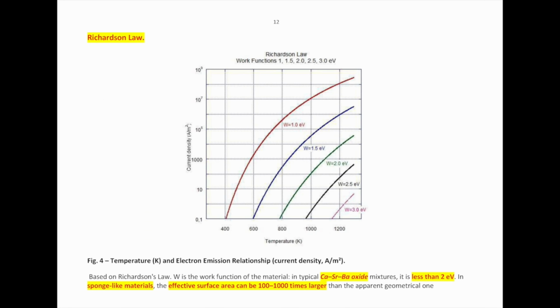Here is shown the usual curve of low work function materials. We are working in this region: barium, calcium, strontium. And moreover, because the surface is sponge, the effective area is 100 times larger.